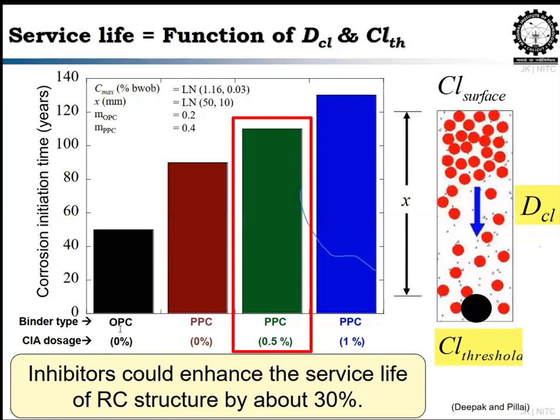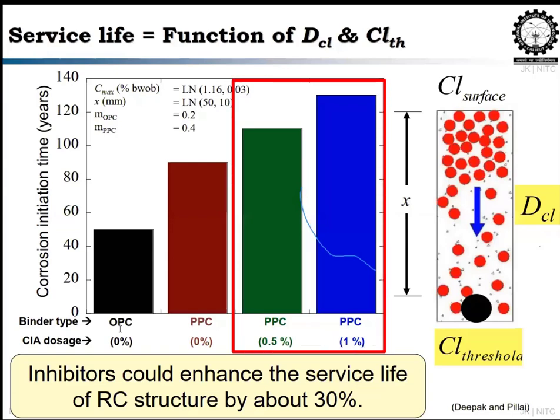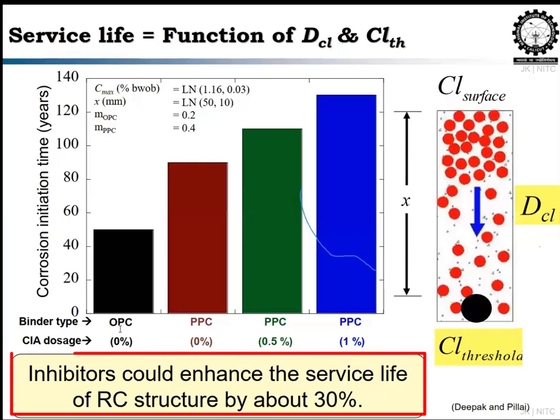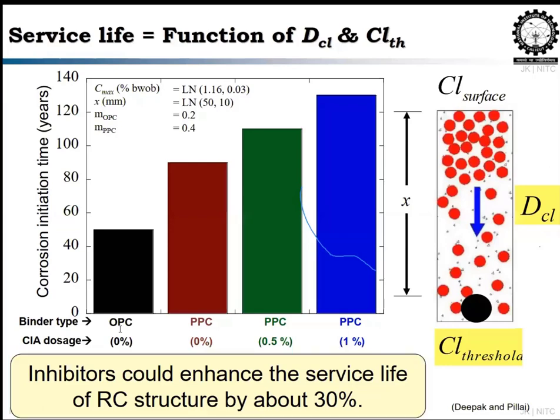If you use corrosion inhibitors to further increase your service life, with 0.5 and 1% dosage, you can see it goes beyond 120 years if you go for 1%. It means you can increase your service life by 30 years by changing the case a little bit, which is going to cost you a little in the beginning. That is the very important thing.